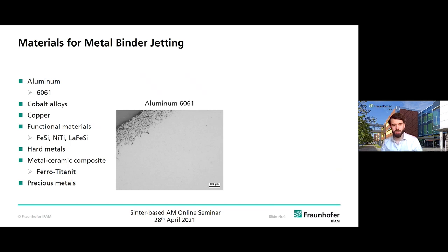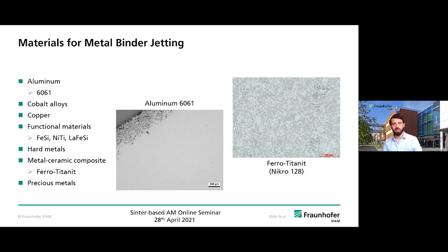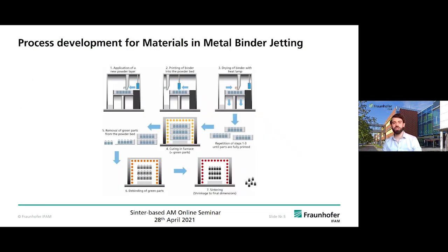We did more research on metal ceramic composites. One example is ferro-titanit, where you have a matrix with titanium carbide inside, up to 40 to 50 volume percent. So it's really wear resistant compared to other materials. And the last point is precious materials that we have also been looking into, especially in metal injection molding in this case. So that's the materials for binder jetting.